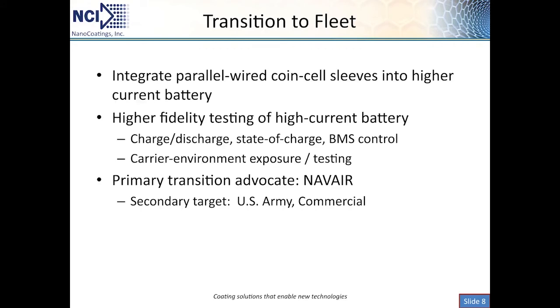Our approach and remaining tasks to transition this technology to the fleet are shown in this chart. The requirements do call for high current battery output. In order for us to get there, we will have to do one of two things: either integrate parallel wired coin cell sleeves into the battery architecture, or increase the amount of active cathode material in the layers. And we're looking at both of these options. We will be required to do higher fidelity testing of the high current battery, including traditional charge discharge, state of charge status, and BMS control of the battery. We do require the battery to be exposed to a carrier environment, followed by some testing. The primary transition advocate is NavAir for fighter aircraft, as we stated, for emergency backup power and possibly for engine start. Secondary target is for the U.S. Army and also some commercial markets.